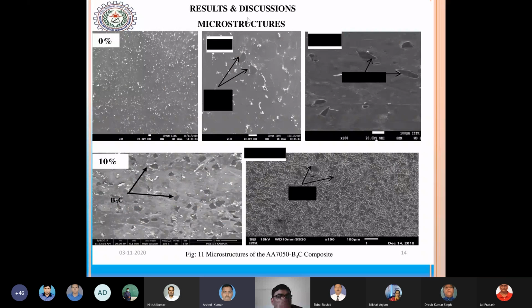And they have studied the microstructures of those aluminum-based metal matrix composites, and they have observed that the main factor is the distribution in the structures. If you maintain the distribution of the particles properly, you will get better strength. If the distribution of those particles is not good, see in the case of Arvind's work, these are the B4C particles.